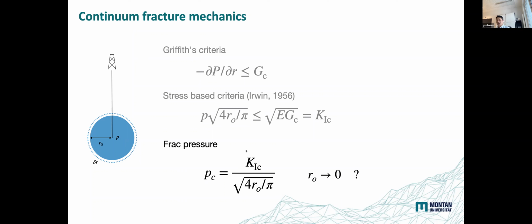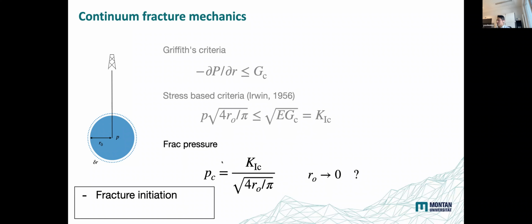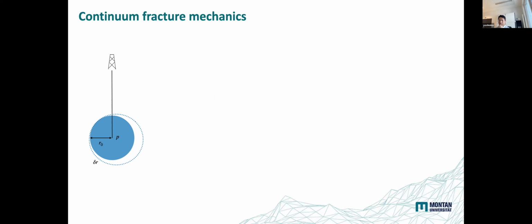But if we look at this expression, what happens if we set the initial size of the crack to 0? You see that the frac pressure becomes infinity. This is one of the drawbacks of Griffith criteria. The fracture initiation cannot be predicted if we use Griffith criteria. So we always have to assume some small size fracture, and this is also true when we do simulation. We have to assume some initial small fracture. We put some seed of the fracture in order to initiate the fracture.